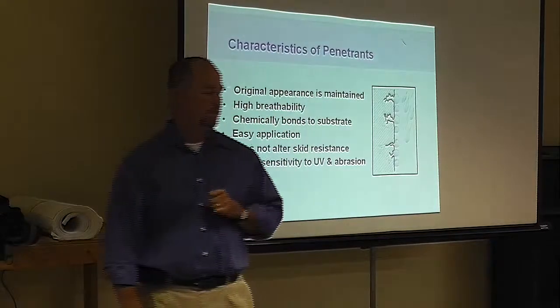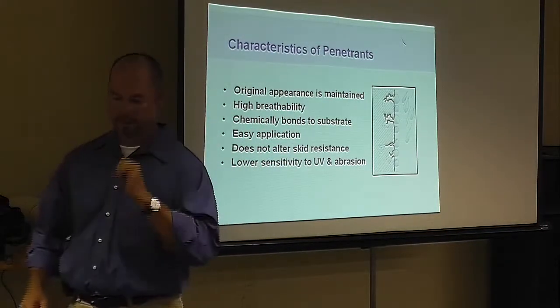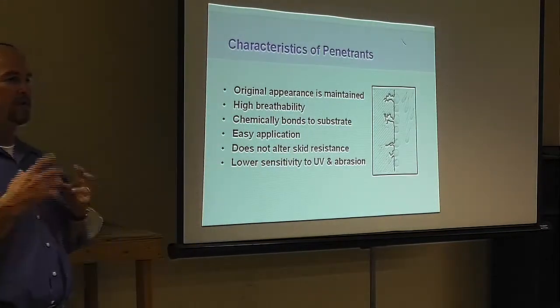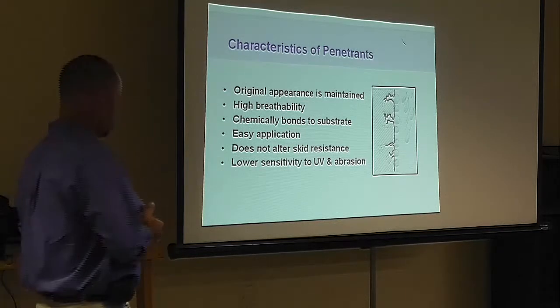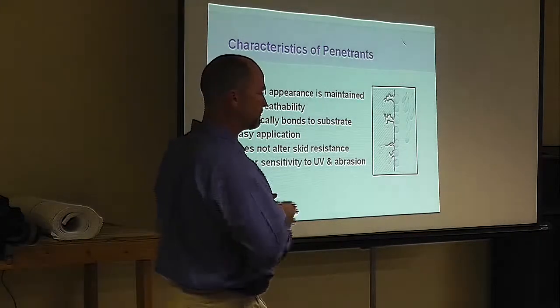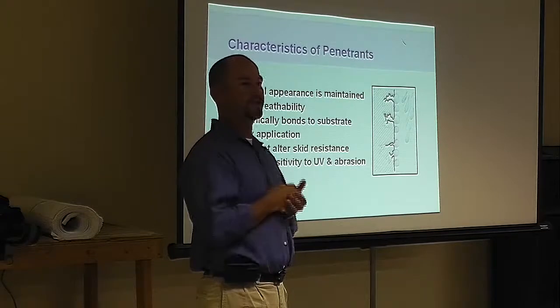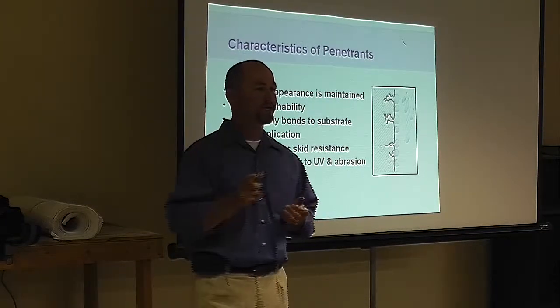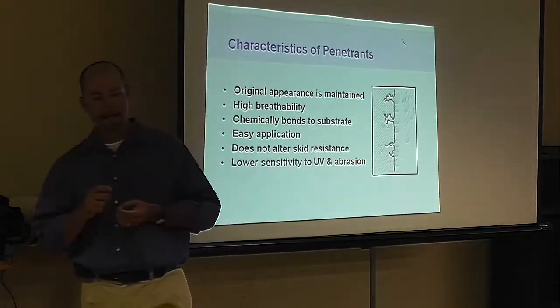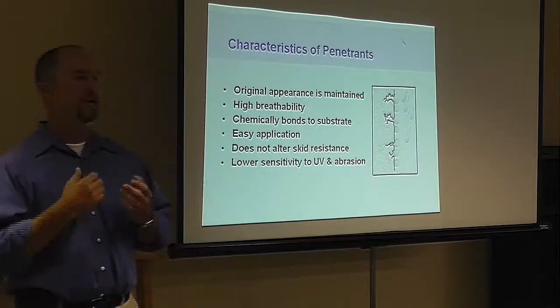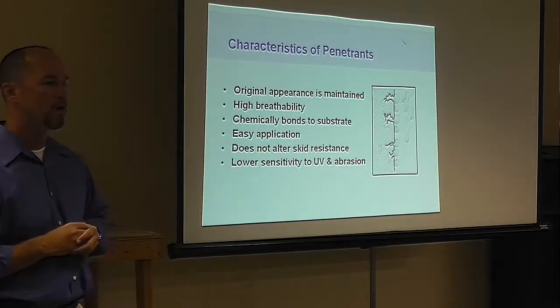Now, the characteristic of your penetrating sealants and water repellents is that they chemically bond to the substrate. They become part of the substrate. They don't change the appearance when they're applied correctly. They don't change the appearance of the substrate, and they protect that building. They don't break down in UV because they become part of the block.